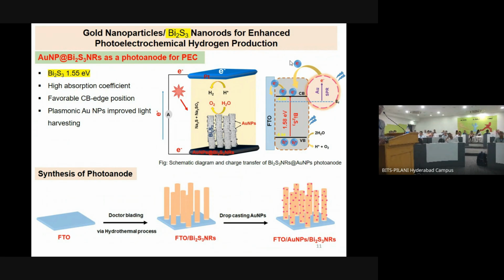But if you look at the cutoff region which you have, that's where the bismuth sulfide, say for example, kind of rods which he has prepared. And if you try to see, the absorption happens at the edge of the visible and NIR region. This material has a favorable conduction band edge position for the hydrogen evolution to happen. And now on this, you can try to decorate a noble metal nanoparticle. Then you can suitably construct the band edge diagram by using the combination of cyclic voltammetry and UV visible. Then the simple way you can make a catalyst, or the electrode, is we make one square centimeter.